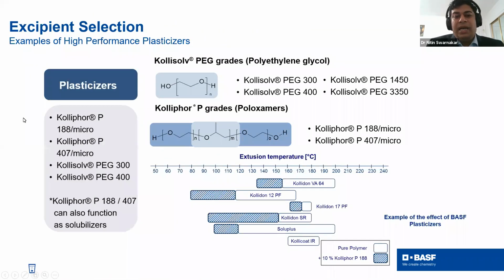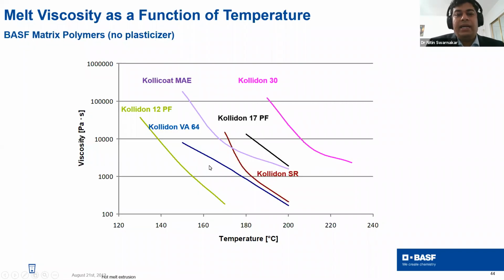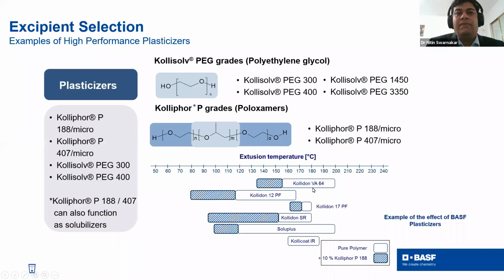Now coming to one part that you have seen: we sometimes need to operate at a higher temperature, maybe starting from 155 to 200 degrees centigrade for Kollidon VA64. But if you add a plasticizer, what they generally do is interact with the Kollidon VA64 polymer and lower the overall operating temperature. In VA64, you can see it decrease the temperature by 20 degrees centigrade, and sometimes more than 20 degrees centigrade. This is very important because if your API is sensitive, you can mix in the plasticizer and then do the extrusion much more easily. We have Kollisolv PEG grade polymer, which is in liquid form.